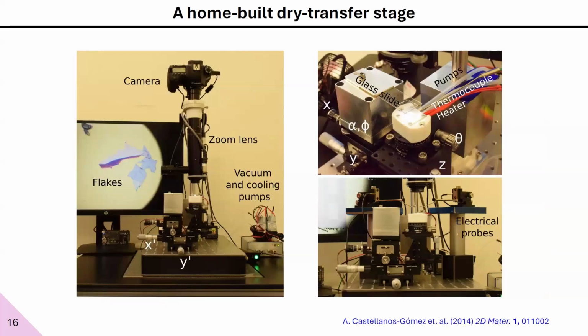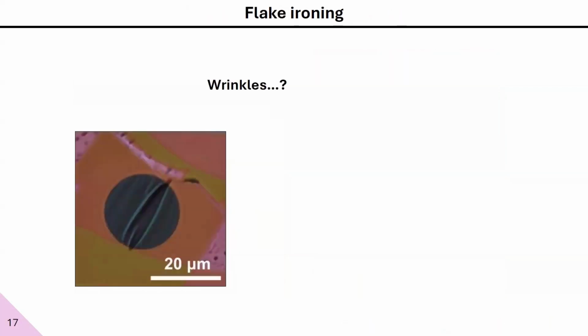For this, we have used a home-built dry transfer stage, which is basically our camera with a zoom lens. We have temperature control here, thanks to a heater and a thermocouple. And basically, it's two sets of manipulators that we use for precise alignment of our flakes over the target location. This design was inspired by a previous design by Andrés Castellanos, and it actually helped us a lot in our research. So we take this equipment and we produce a bunch of suspended samples.